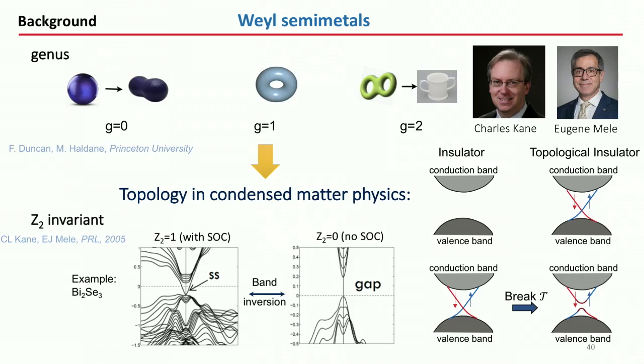So when that particular semiconductor or insulator or material ends at an interface, let's say even vacuum, the system gets confused at the interface because now you have to go to the normal system. And when you go from one genus to the other, one topological invariant to the other, you have to gap out the system. And those states can only occur at the interface of these two systems. So you create these surface states. And this is what happens in a topological insulator. But in a topological insulator, you have this type of dispersion only on the surface. And this leads to some complications because transport and all those properties become hard to measure, because it's very hard to figure out if it is coming from the surface or bulk.